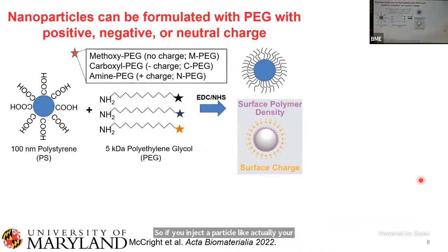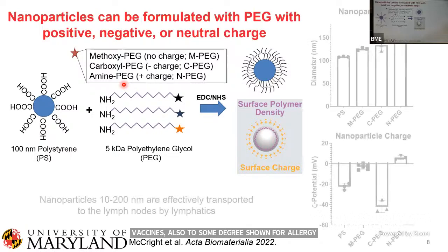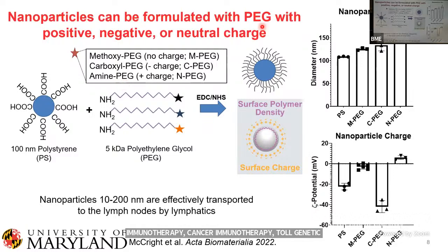And so we started out with just making an array of particles. We use polystyrene beads. They're just really easy to work with, to functionalize. They're standardized in terms of size. So you can modify them with things like polyethylene glycol, everyone's favorite polymer. And so we coated those particles with polyethylene glycol, either that has no charge or that has an end group of a carboxyl, so a negative charge, or an amine, so you can have a positively charged particle. That way you can get charge on the surface, as well as having a coating that's known as the stealth coating. And so we made this array of particles around 100 nanometers in size.